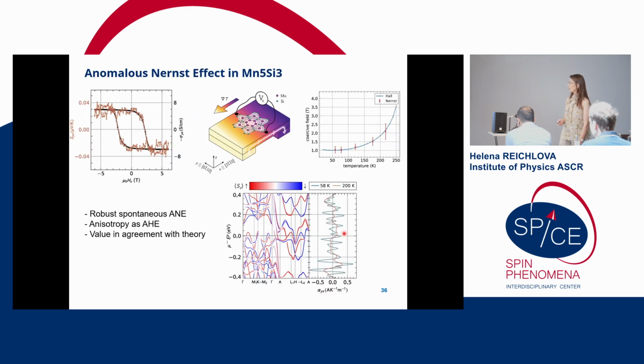And what we see here is an example of our data. The black curve is the anomalous Hall effect from our Mn5Si3 films, and the orange data on top of it is the anomalous Nernst effect. Indeed, we see that it has the same anisotropy, the same characteristic increase of the coercive field with increasing temperature, and it's in good agreement with the theory, again provided by our colleagues from Mainz.